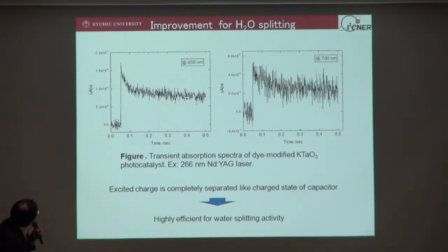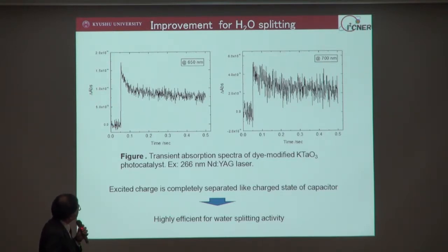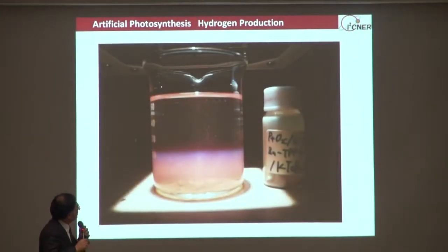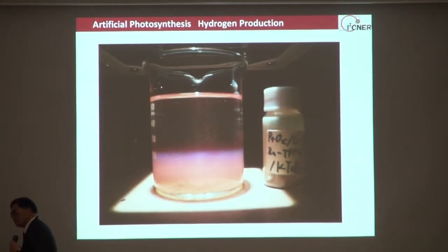This is the transient absorption spectroscopy of the dye. And as you can see here, once the dye is excited, the separated charge never recombines. This means the positive charge, hole and electron, after excitation, never recombine. Therefore, the excited charge is completely separated, like the charged state of capacitors. And this state is quite effective for highly efficient water splitting activities. But the reason for such a small conversion efficiency comes from the energy level of the inorganic materials.